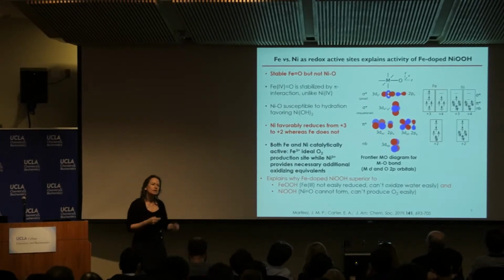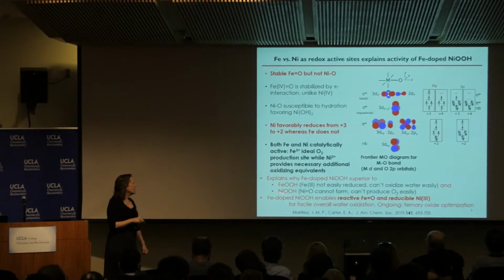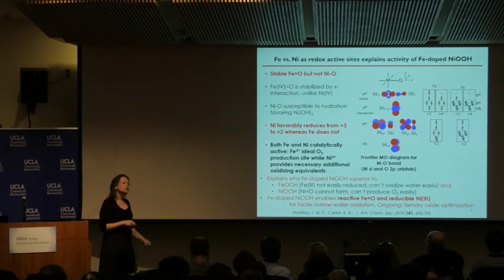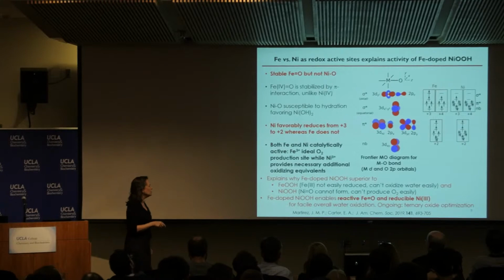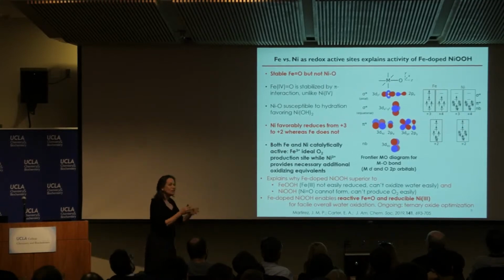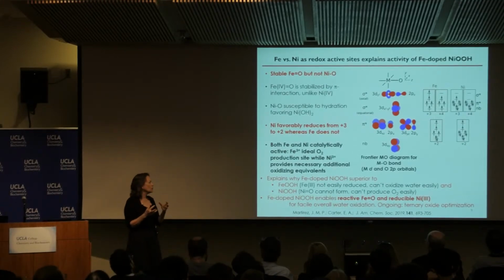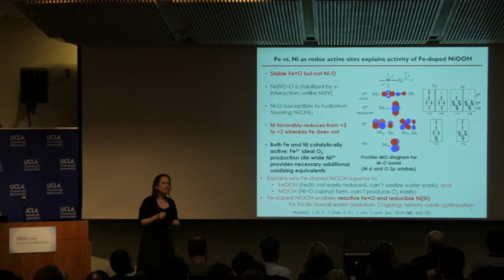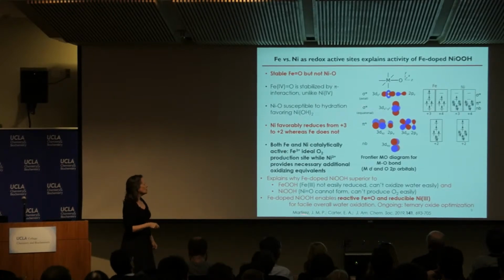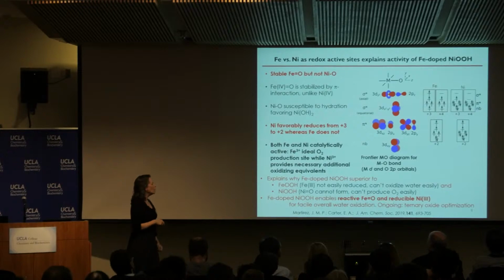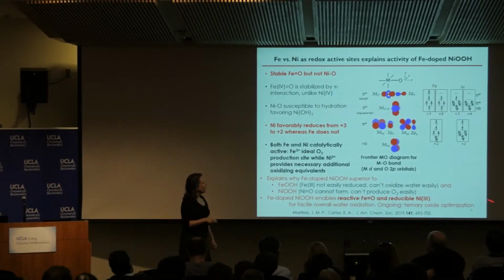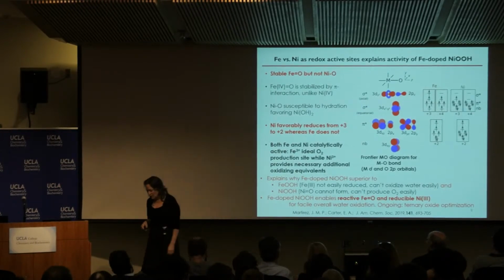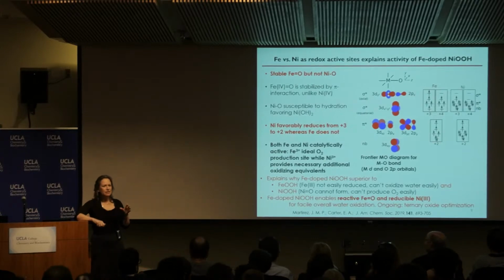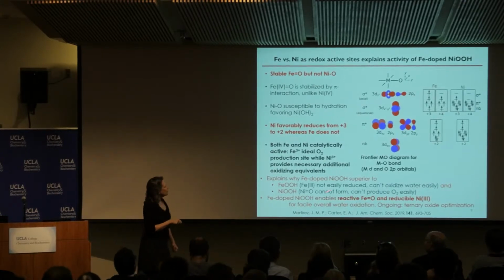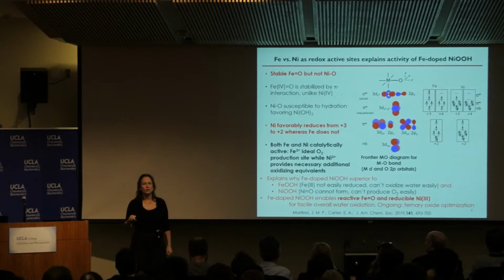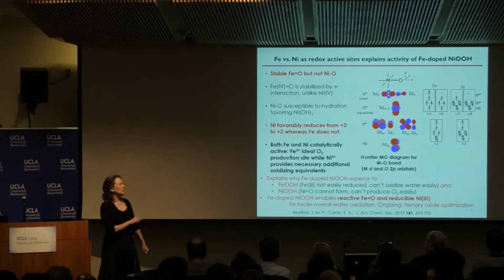So you have this Goldilocks situation where iron-doped nickel oxyhydroxide allows you to form this reactive iron oxo, and having it in the host of this reducible nickel 3 that can pull electrons out of water is what allows you to have this facile water oxidation. And in fact, we have work going on ternary oxides to take advantage of these insights to improve the process further. Enough said on that.